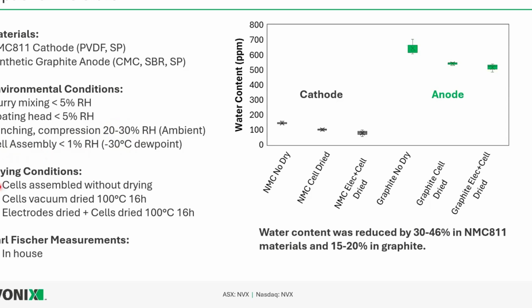So the drying conditions, what we do with these electrodes after they're coated is we do dry them, and we dry the cells. Cells assembled without drying compared to cells vacuum dried at 100 Celsius for 16 hours. And then drying the electrodes separately, assembling the cells, and then drying the cells all together. And you can see with some in-house Karl Fischer measurements over here that you can see the effects of drying, where we were able to pull out 30 to almost 50% of the moisture out of the cathode materials.